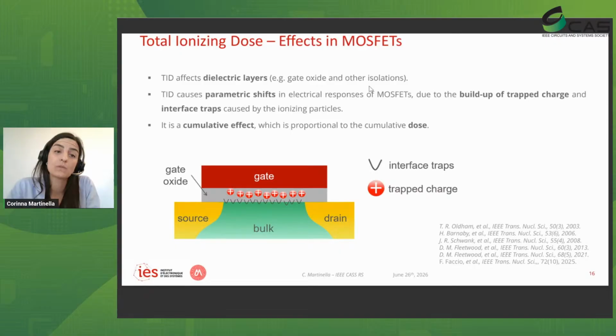It can cause a parametric shift in the electrical responses of the MOSFETs due to the buildup of trapped charges and interface traps that are caused by the particle that is ionizing the material. It's a cumulative effect, as we said, which is proportional to the cumulative dose.